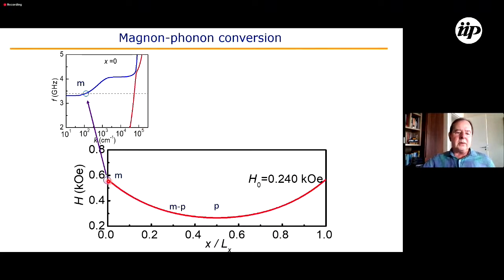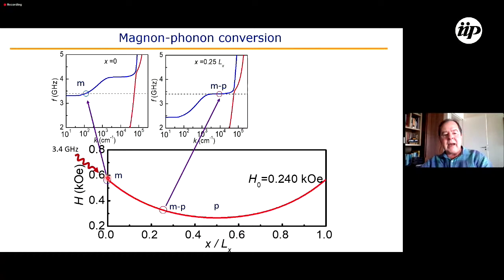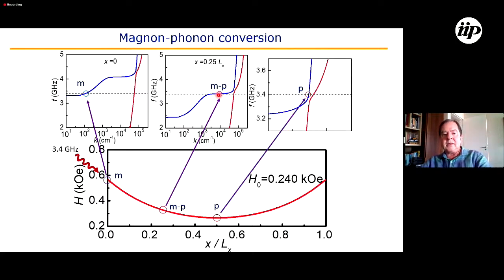At this point, the magnetic field is high, so the dispersion relation is high, and for this frequency, 3.4 gigahertz, we excite a magnon. So we use 3.4 gigahertz microwave radiation. We excite a magnon, but then as the magnon propagates down the hill, the dispersion relation is lowered, and then it becomes a mixed magnon-phonon excitation.